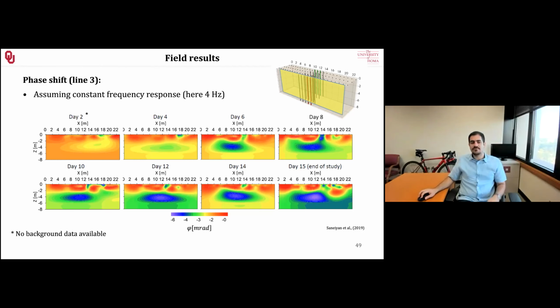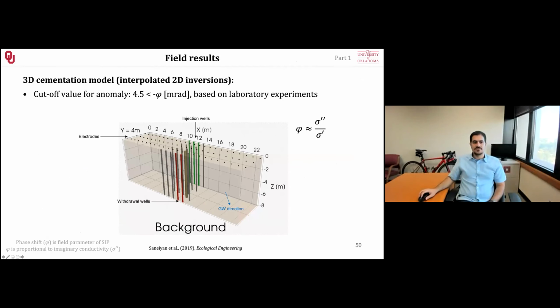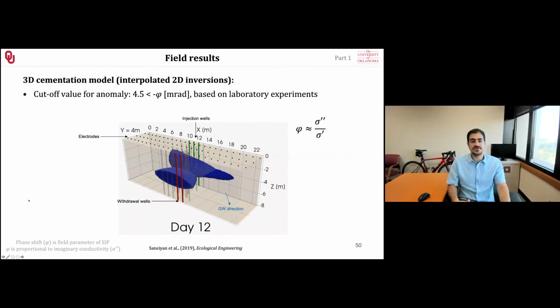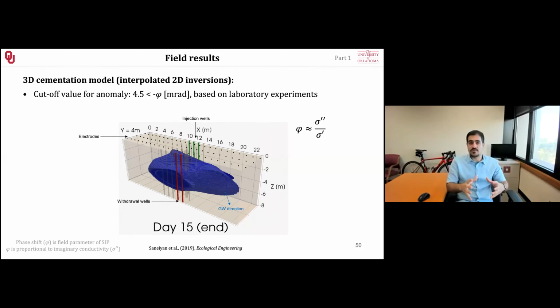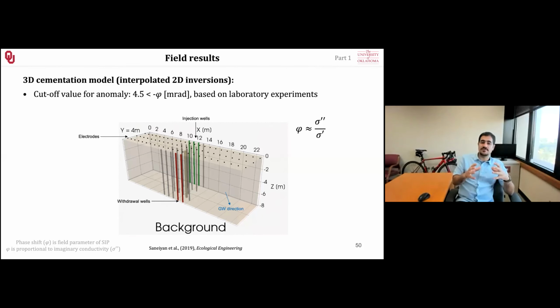Nothing but a smaller amount. If we show that in a three-dimensional view and exclude all the surrounding, you can clearly see the calcite precipitation occurring exactly where we want it to happen. And our geophysical phase shift measurement is basically similar to the imaginary conductivity, assuming that the real conductivity, which is because of the water conductivity, hasn't changed and remains constant. We are clearly mapping the subsurface affected by MICP.